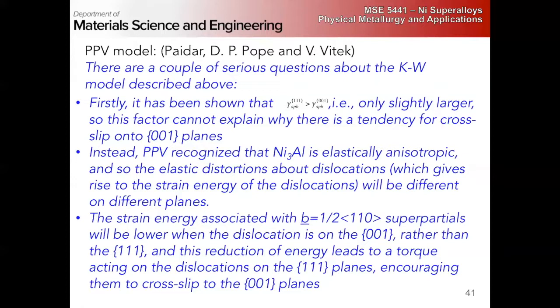So it's a much more complicated picture, but generally the details behind it are more complicated, but the big story is basically the same. At elevated temperatures, cross-slip becomes easier, and there's an energetic driving force to drive them onto cube planes where they're sessile rather than the 111 planes where the dislocations are mobile, right?